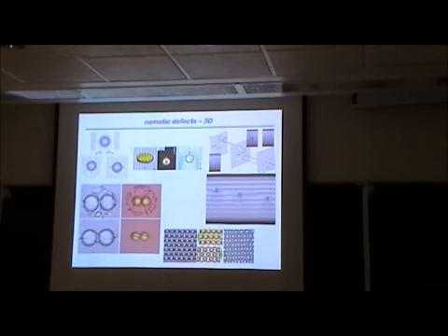So this shows an example of this structure. You have a microparticle with this point defect. Then you have a gold nanoparticle treated with an alkyl monolayer so that the director wants to be perpendicular to it. This is actually a gold nanodisk, so the micron particle is trapped to the nanodisk at a defect.